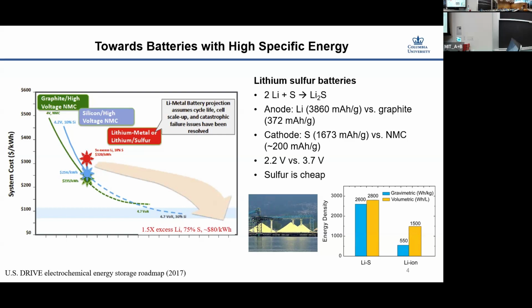Electrodes in lithium-ion batteries, for example, the lithium is 10 times the graphite in current lithium-ion batteries, and the cathode is also almost 10 times. Although the voltage is lower, the overall theoretical energy density of a lithium sulfur battery could be 3 to 5 times that of conventional lithium-ion batteries. That's why they are very attractive, because with a high energy density, you can extend the mileage range of electric vehicles. Also sulfur is really cheap. It is a byproduct of the petroleum industry, so the cost in principle can also go down a lot.